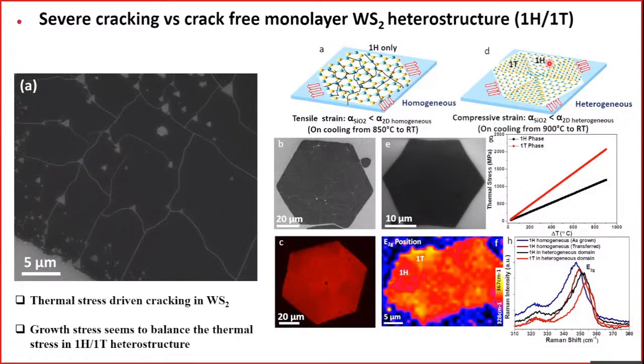But if you have a 1T and 1H mixed phase, the in-plane heterostructure, even if you have a defect, we still don't see this kind of fracture. That was counterintuitive. Generally, we think heterostructures are prone to strain and so on. In this case, heterostructures are more stable compared to the homogeneous structure. Then we carefully looked at the Raman spectroscopy and found that because of the 1T, 1H coexisting phase nature, this biphasic 2D material intrinsically has some compressive strain.